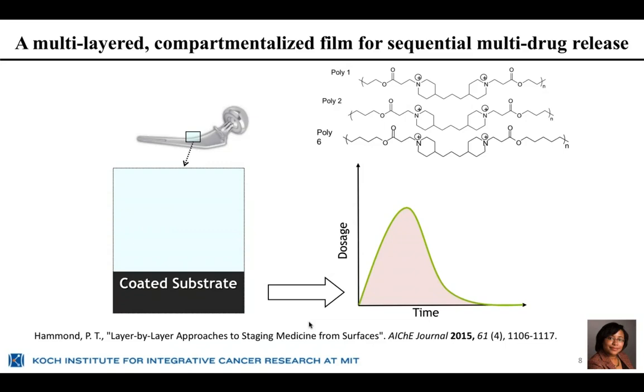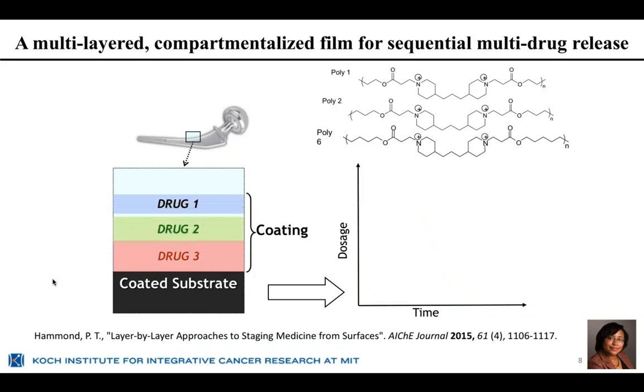same fashion. One of the nice things about layer by layer assembly is that if we have a nice set of, let's say, degradable polymers that can be incorporated into the film based on charge, for example, these poly-beta amino esters, which are shown in the upper right-hand corner, which have ester groups that are degradable, but also these nice charged groups, you can tune the degradability of these polymers and then build up films by alternating them with the active agent. And in our case, those active agents may be proteins, nucleic acids, or even small molecule drugs. So you can imagine that you can incorporate different drugs with different degradable polymers, and they will each have their own unique rate of release from the film.